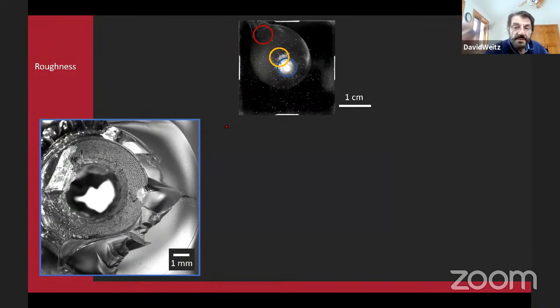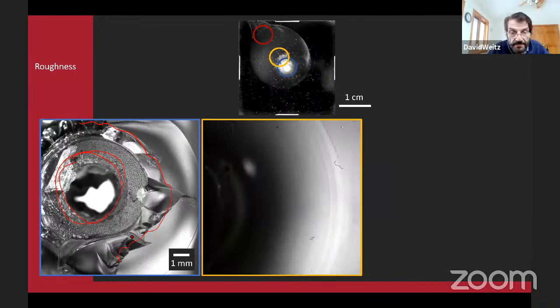Well, we can go and we can image the sample after it's torn apart. So here we can see that in this case, there is some real roughness. This is where the fluid is coming in. There's some real roughness, which is indicative of some nucleation process. You have to have somewhere where the crack begins to nucleate. Then if we look further out, so this is the sample here. This is the square sample. And this is this image, the blue image. And now I'm looking further out. I'm just taking images in this place. This yellow is here. It's coming from this direction. The water is coming from this direction. And notice you start seeing these rings.